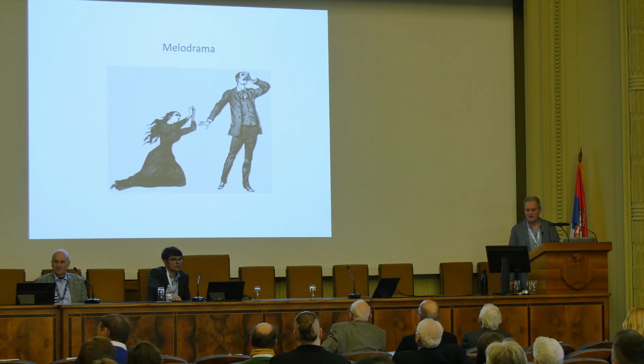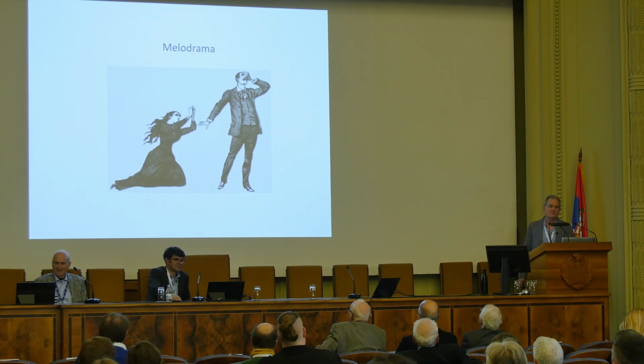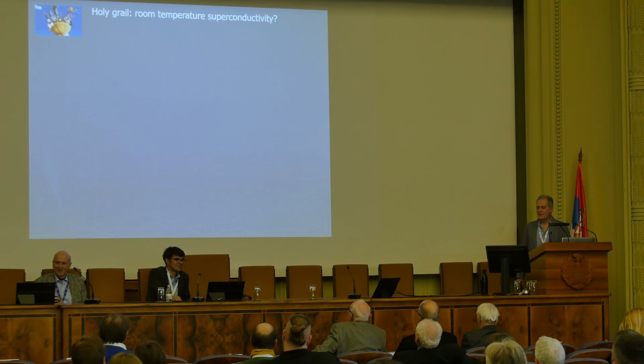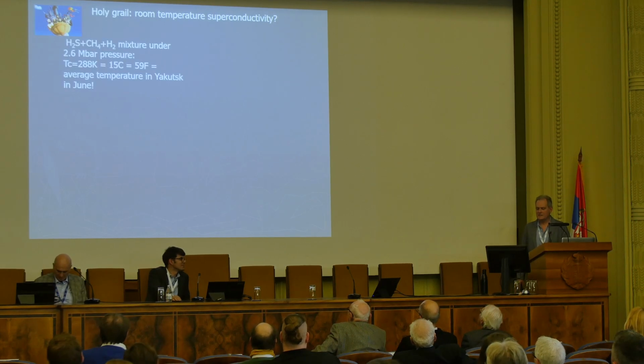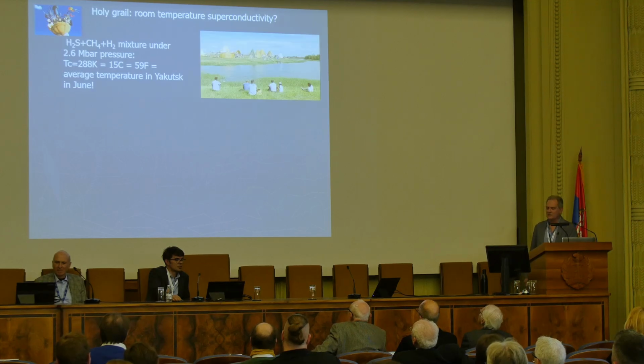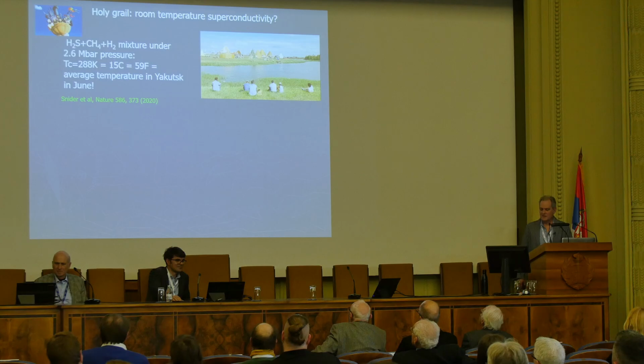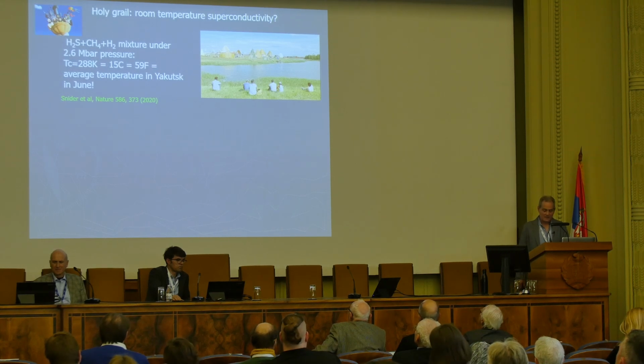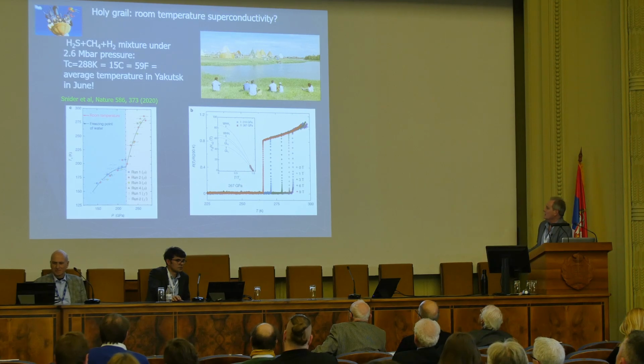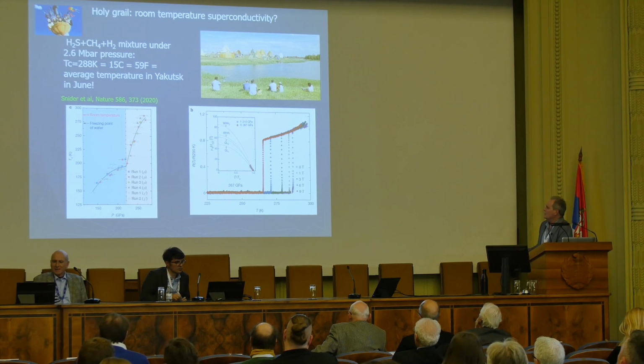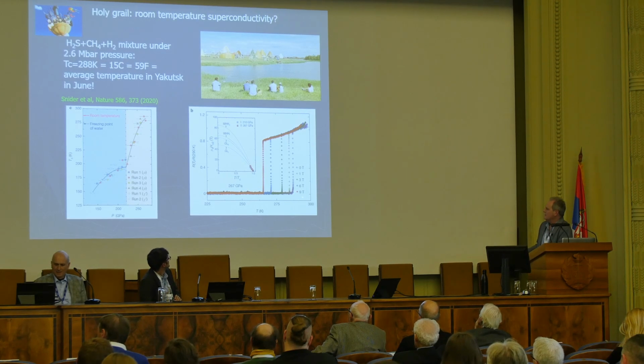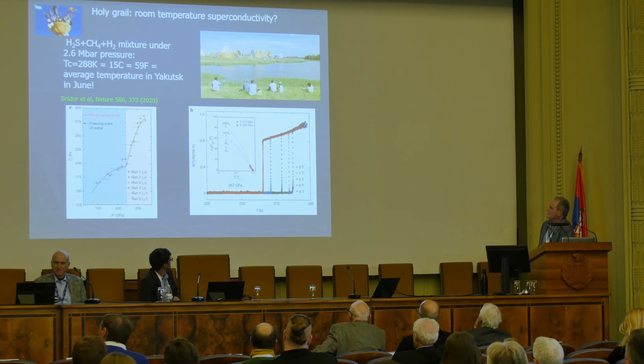But let me go on and talk to you about what you may have heard about, which is the melodrama that took place in the field shortly thereafter. That was initiated by someone who was searching very hard for room temperature superconductivity. And this, by the way, would be the average temperature of Yakutsk in June, just to make the comparison. This is the holy grail of the superconductivity field, according to some. And this paper appeared in Nature from Snider et al., which is a group in Rochester, led by Ranga Dias. And he found beautiful transitions at room temperature, basically, close enough for government work, all the way up here for zero field. That's this temperature here. That's 290 Kelvin or something like that.